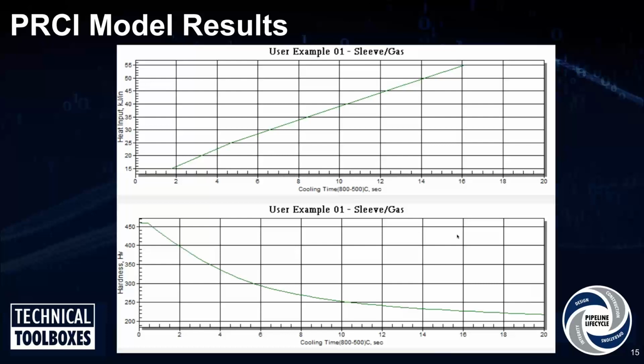So that's what this model is good at doing. It allows you to predict your minimum heat inputs and your maximum heat inputs from a burning through perspective. And then you just have to relate that to your welding procedure and communicate to your welder, hey, you have to weld at this current range, and you have to be within this, say, this travel speed range to be able to comply with the welding heat inputs that the model predicts to be safe for your situation. So that's how the whole model ties into mitigating the risk of in-service welding. And that's all I had to talk about.